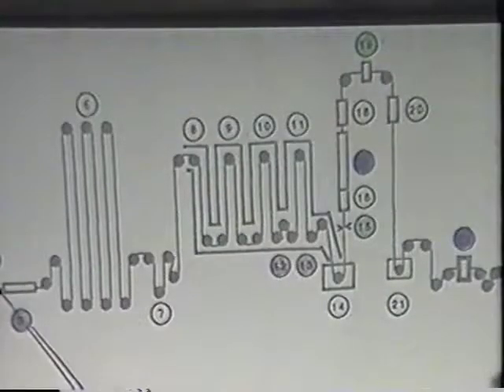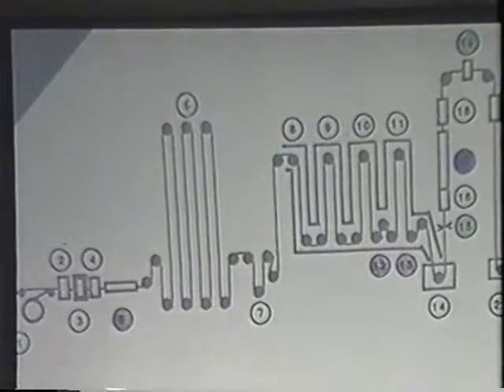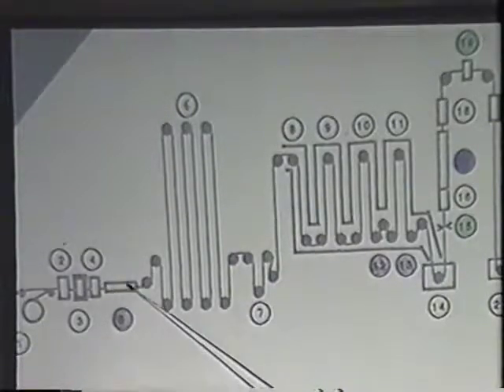So we have it set so it'll chop off as much scrap as needed until it gets on gauge. If it's 20 foot of scrap, it chops it off, sees it's on gauge, goes to weld it up. If it's 100 foot of scrap, it just keeps chopping until it's on gauge. So we shouldn't have any problem with off-gauge product on the hot dip line because of the tandem mill ends. And it does the same thing on the tail end also. So they'll weld it up together. So now you've got a weld going through.